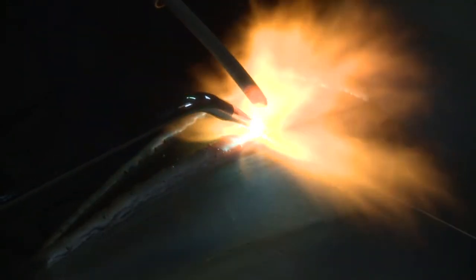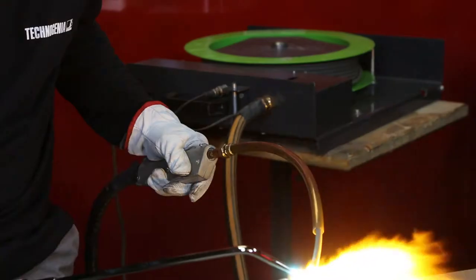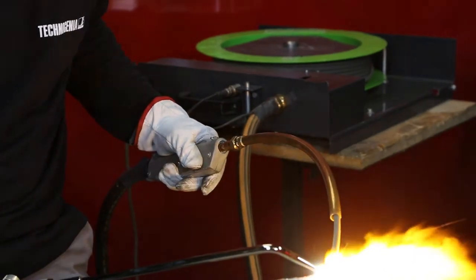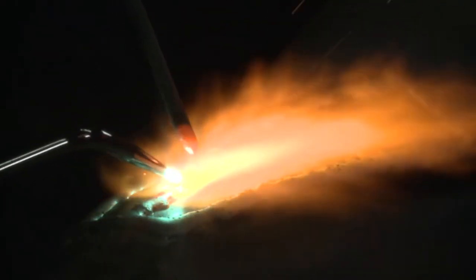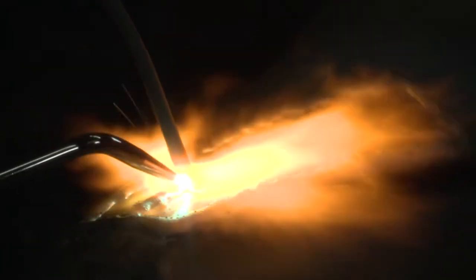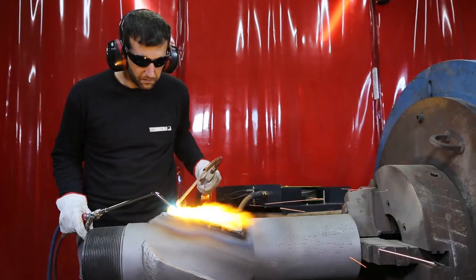Because of its unique cold crucible process, Technogenia is able to produce spherical cast tungsten carbide with a hardness of 3,000 to 4,000 HV.